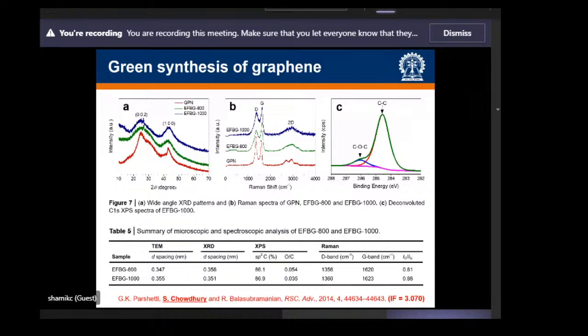So we compared the values, and we saw that the Raman ID/IG values, the XRD d-spacing, and then the d-spacing as observed from transmission electron microscopy were nearly identical to graphene that is produced in the laboratory by the conventional technique. So because of this, we came to the conclusion that this material that we have derived from the waste biomass through hydrothermal carbonization followed by pyrolysis is actually a